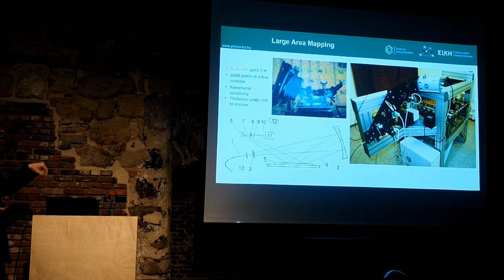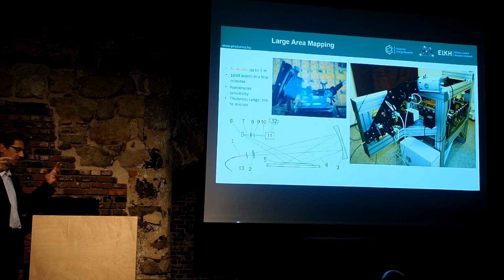Otherwise, if you just move a spot along the surface and measure, even if it's just a couple of seconds or minutes, it is a very long time to map a surface. But because we can measure each point simultaneously, we can measure large surfaces very quickly. And again, for these large surfaces, it has a nanometer accuracy for the thickness, which is very, very important. So there is no other method that can map such a large surface in so many points, so quickly, non-destructively, and so sensitively. And it can be adjusted for a lot of sizes. It can be used even in a vacuum chamber and so on. It could also be used for measuring the thickness of the paint on a car surface